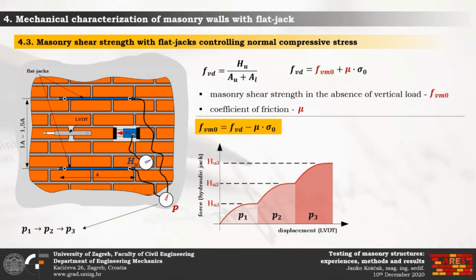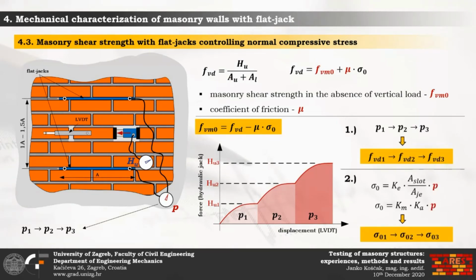In order to do that, we can apply multiple levels of pressure with a flat jack, for example from P1 to P3. For each level of applied pressure, shear tests should be conducted, and the maximum horizontal forces, Hu1 to Hu3, should be taken. Now it's possible to calculate the masonry shear strength for each pressure level. This is FVD1 to 3. And also for each level of pressure, normal vertical stresses should be calculated.